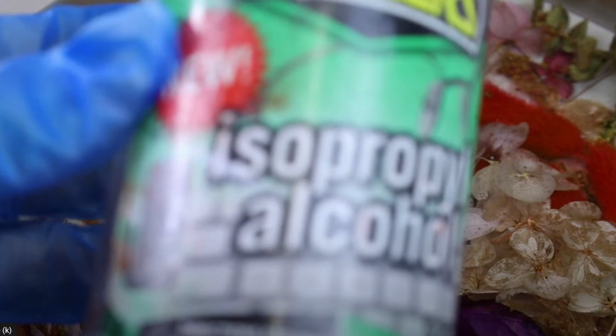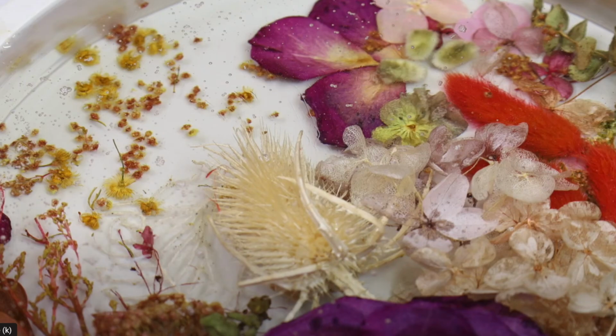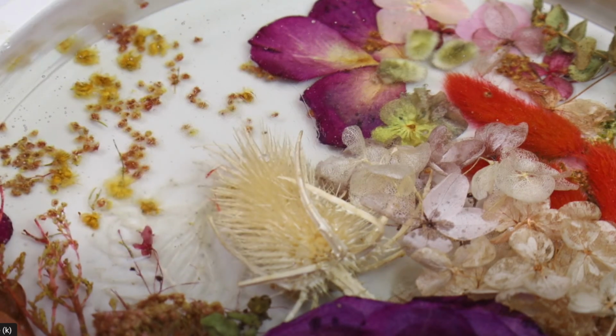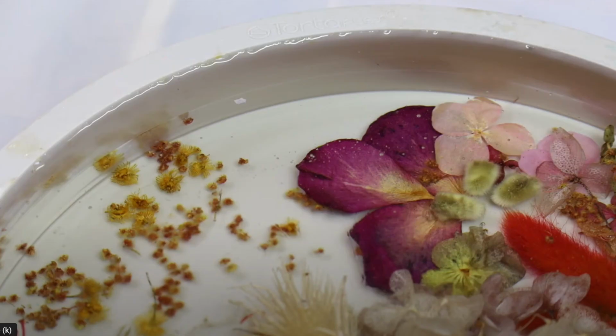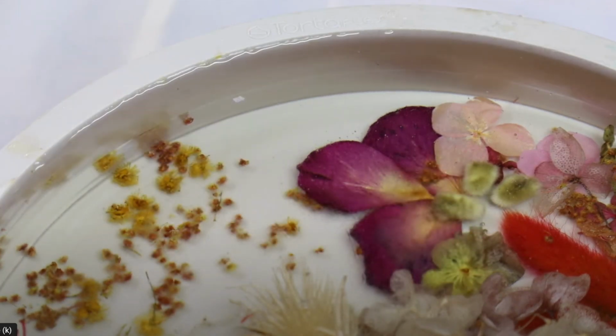Now, if you're worried about using heat, you can always do the alcohol spray technique. Once again, this can only get to the surface layer, so it can only do the bubbles that are on top. And how this works is alcohol, when you spray it across the surface, it breaks that surface tension, which then allows those bubbles that are just underneath the surface to come up and pop. Alcohol will evaporate, so it should not affect your resin as long as you only use a small amount.